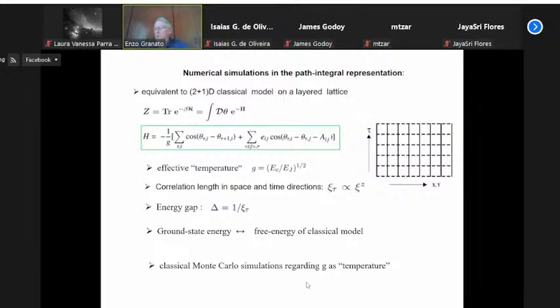The numerical results which I will present are based on numerical simulation with the path integral representation. The path integral representation allows you to map the quantum mechanical model into an equivalent classical model with an extra dimension. So for the model we are considering in two dimensions, you map it to a three-dimensional model, in which this extra dimension is the imaginary time of the path integral transformation. The model that you get has the contribution with the Josephson coupling, and the contribution from the quantum fluctuation of the charging energy gets mapped into the coupling in the imaginary time direction. So it becomes a three-dimensional model.